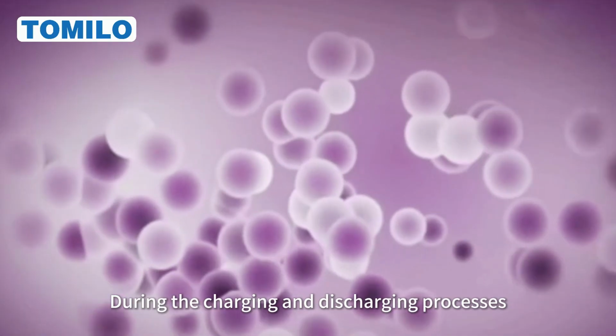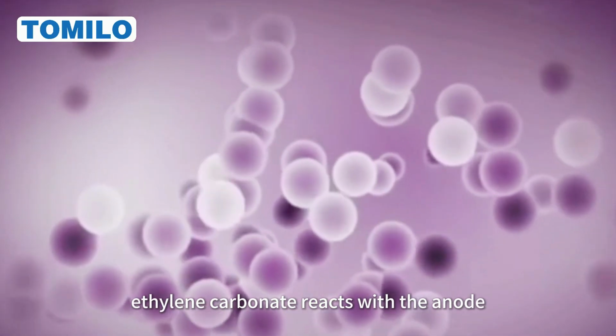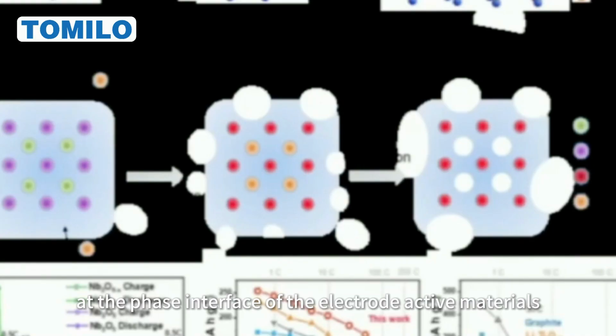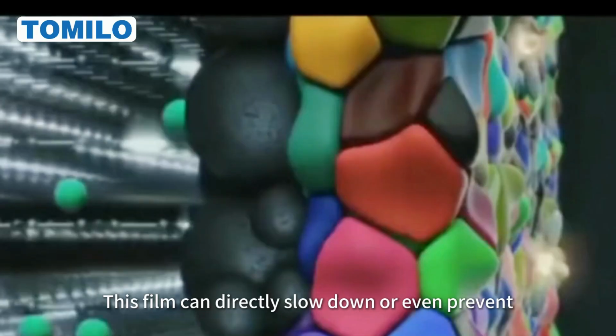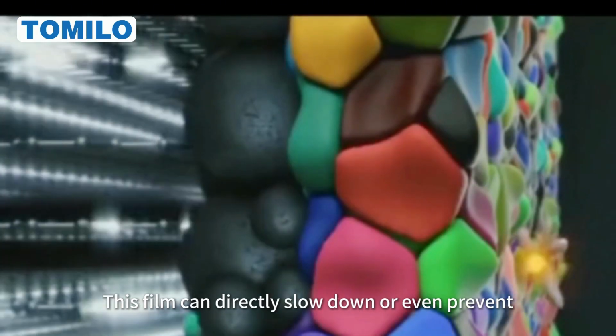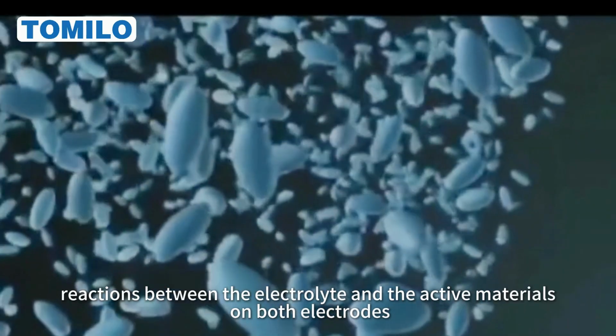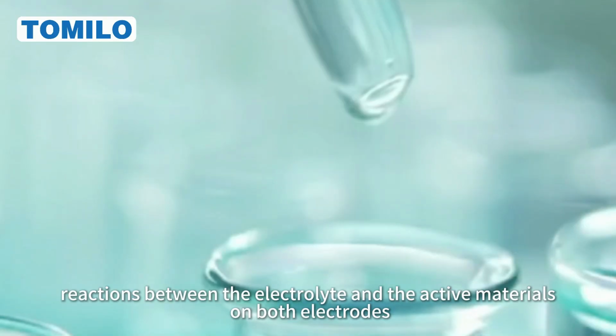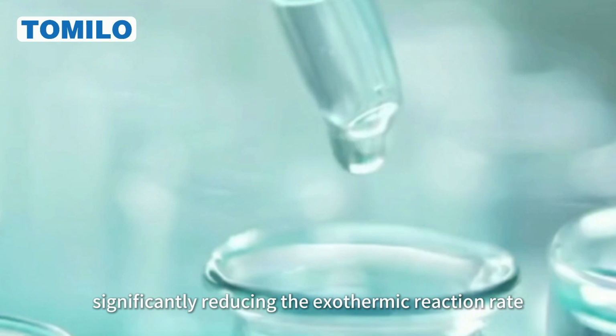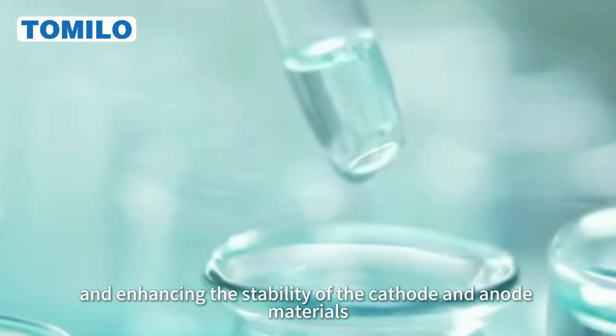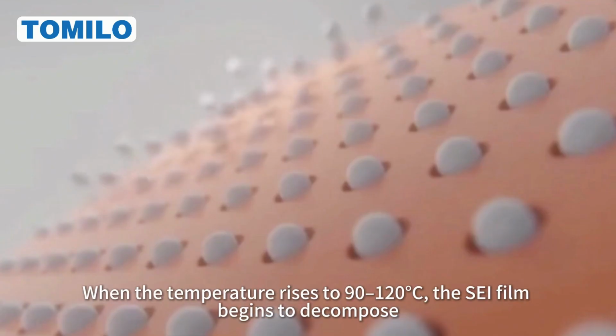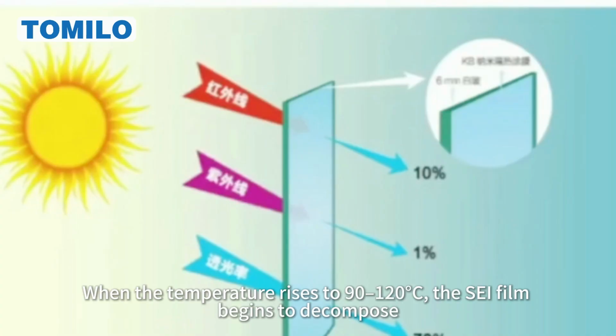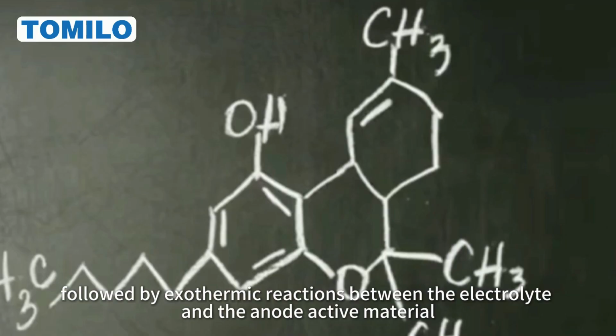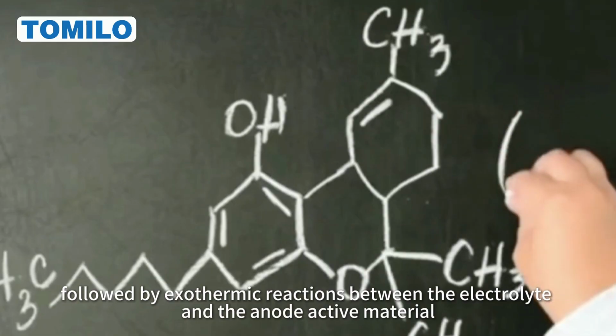During the charging and discharging processes, ethylene carbonate reacts with the anode at the phase interface of the electrode active materials, forming an SEI film on the graphite surface. This film can directly slow down or even prevent reactions between the electrolyte and the active materials on both electrodes, significantly reducing the exothermic reaction rate and enhancing the stability of the cathode and anode materials. When the temperature rises to 90 to 120 degrees Celsius, the SEI film begins to decompose, followed by exothermic reactions between the electrolyte and the anode active material.